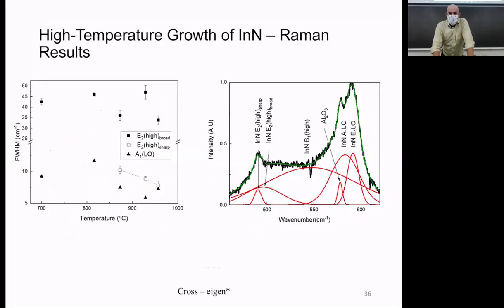We took these results and we plotted them. So you can see here, it's a simple Raman again. On the left, we plotted the E2 high, which is the broad peak. And you can see that broad peak actually kind of does, well, except for that one over there, it kind of does decrease and get a little bit lower, which means that my peak is getting sharper and there's less variance in the way that the structure is. I also took that sharp peak, and you can see that sharp peak is just so much sharper than that broad peak.